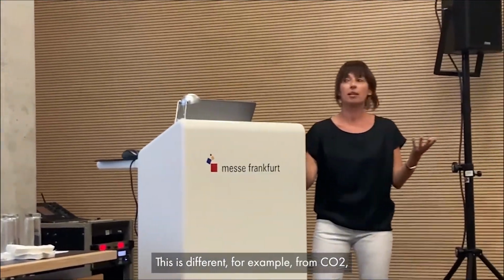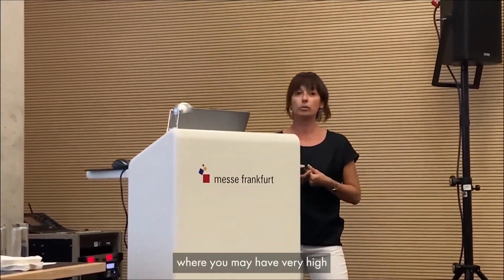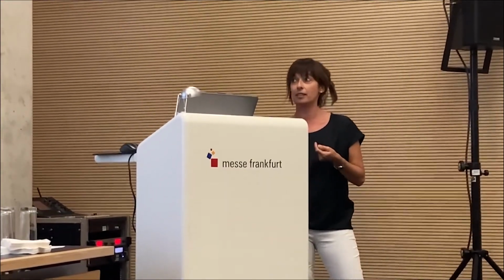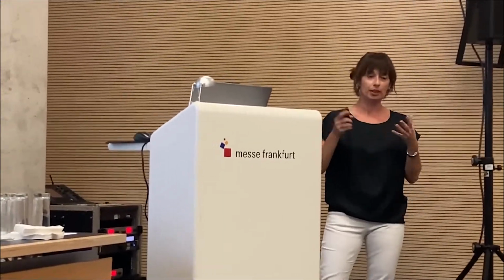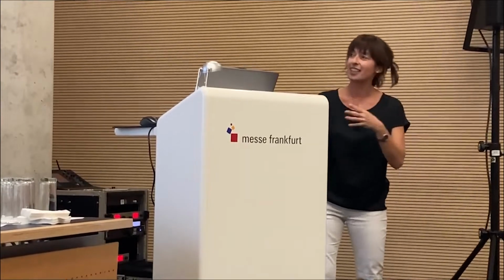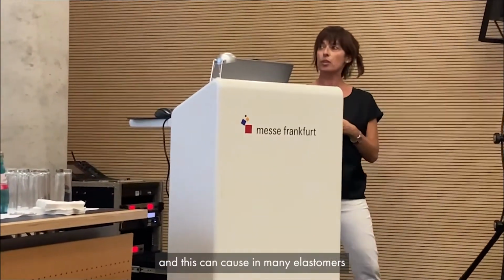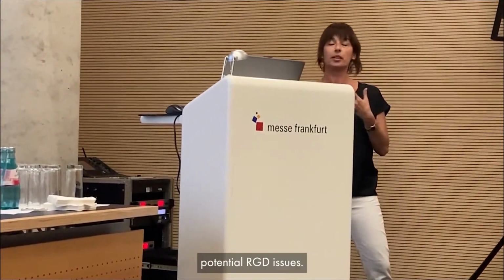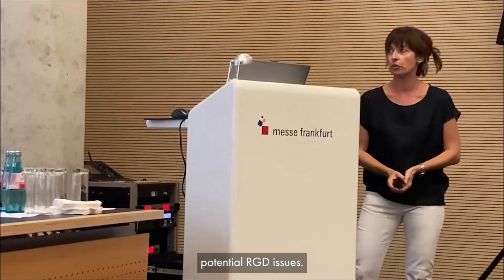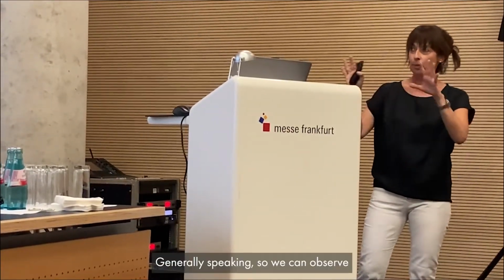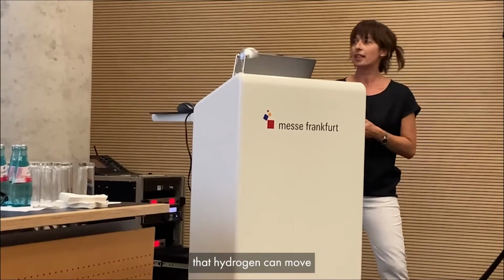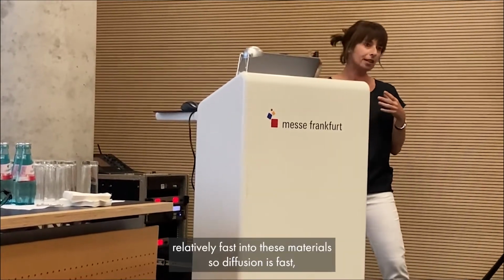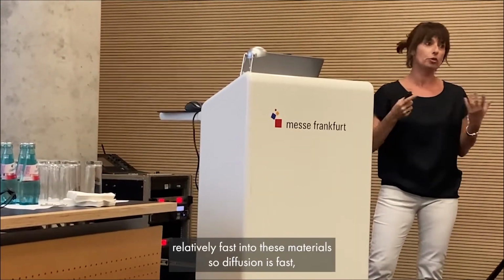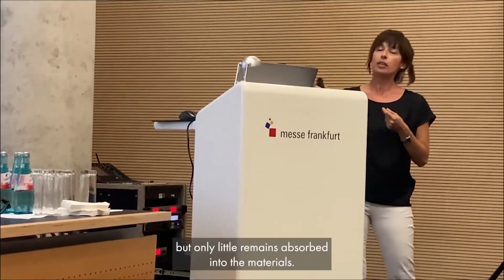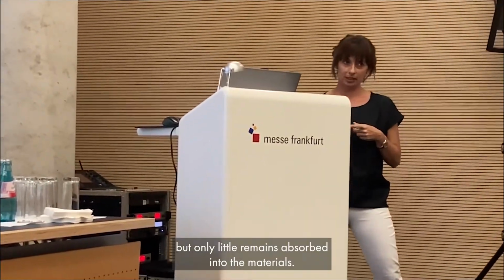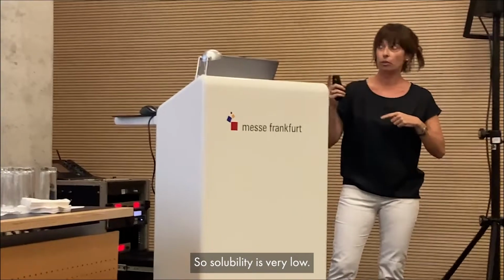This is different, for example, from CO2, where you may have very high diffusion, very high solubility, and this can cause, in many elastomers, potential rapid gas decompression issues. Generally speaking, we can observe that hydrogen can move relatively fast into this material, so diffusion is fast, but only little remains absorbed into the materials themselves, so solubility is very low.